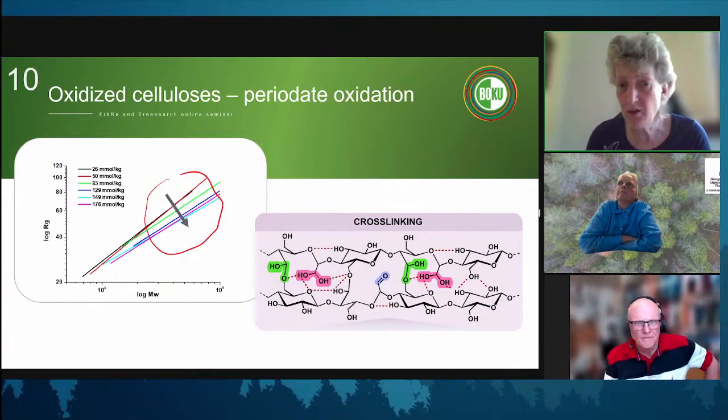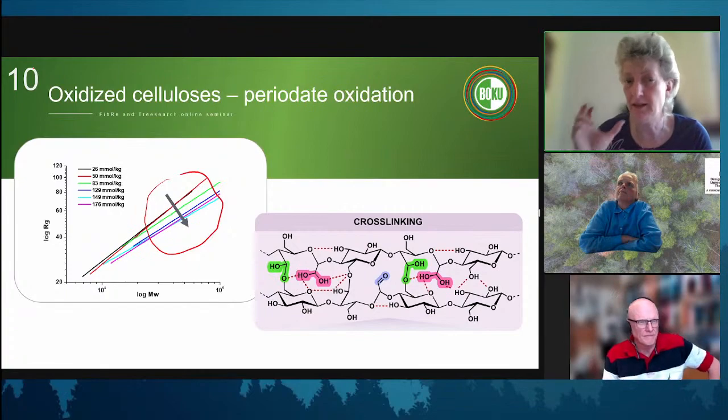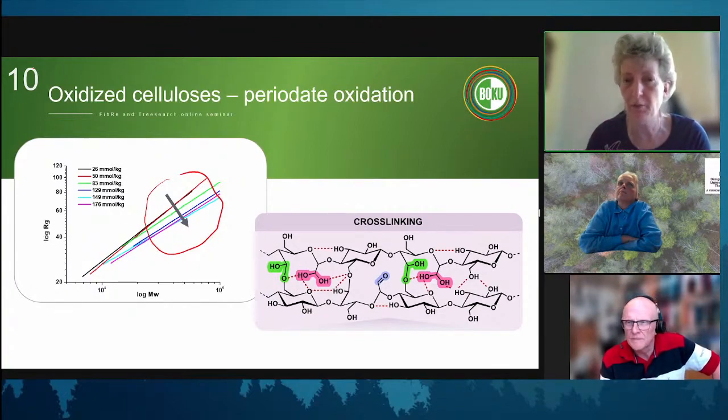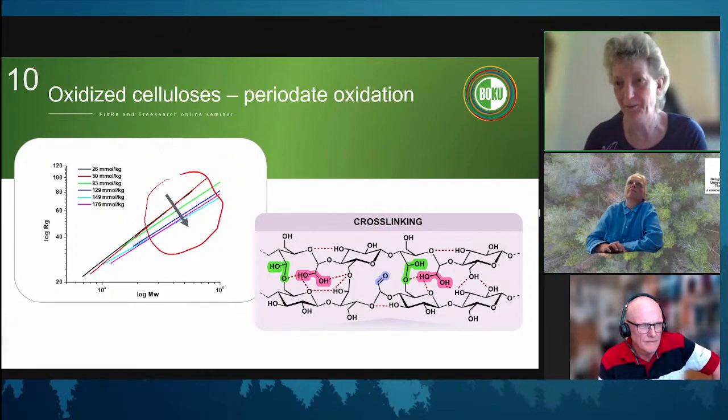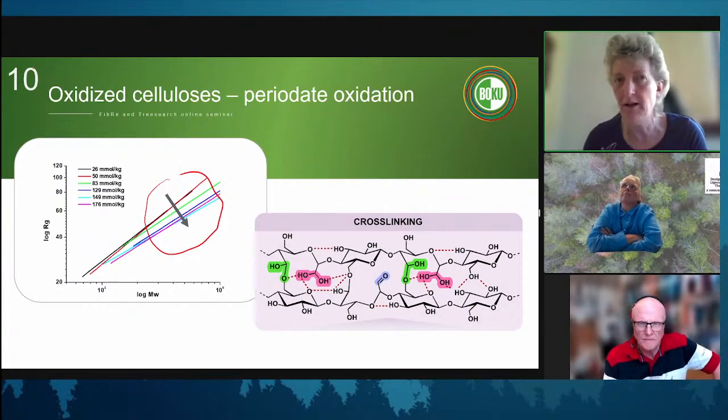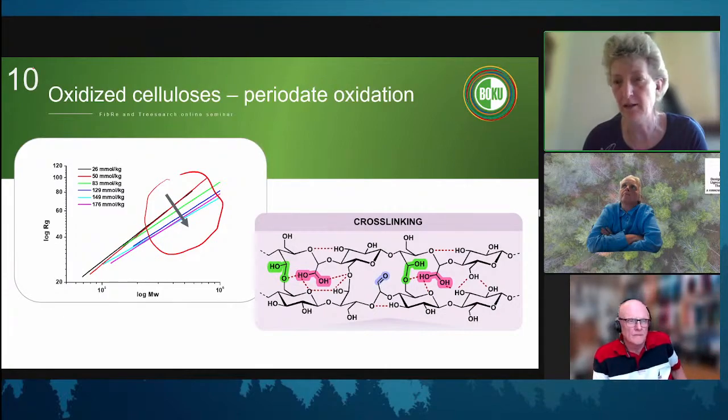So what you see here is basically extrapolated, but over the linear range of the molecule. And if it's not linear, something is wrong, I would say. If the conformation plot is S-shaped or something, then you usually have a very bad state of dissolution. And you already see that from the calibration in the light scattering.